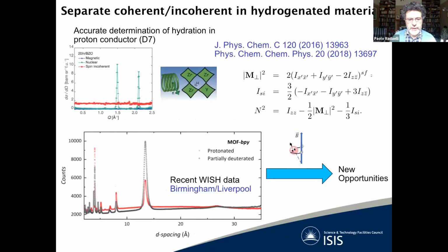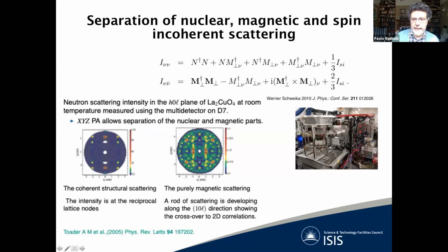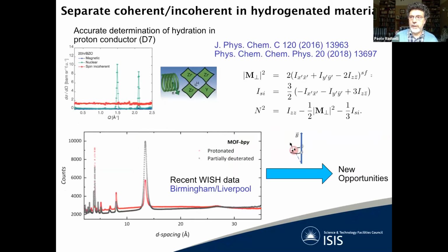More importantly for this community is the possibility to separate coherent from spin incoherent scattering in hydrogenated samples. So as you could see from the previous slide, in the non-spin flip channel, which is the top channel, there is only 1/3 of the spin incoherent. So you suppress 2/3 of your hydrogenous background, which is extremely important in itself for some of these experiments, and in many cases will avoid the need for deuteration. So this is the first benefit of having polarized neutrons with polarization analysis.